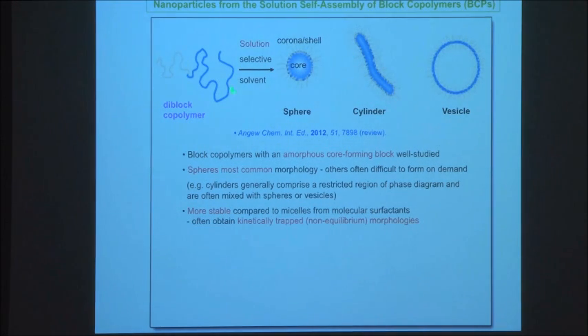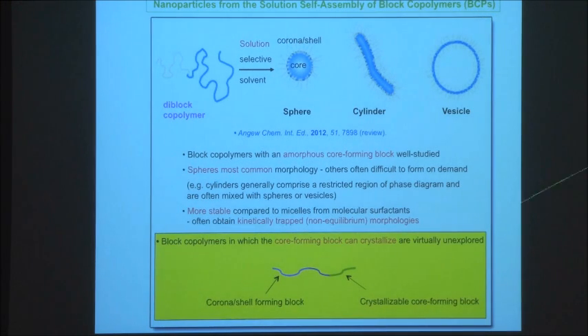So this is well explored where the core forming block is amorphous. And what I'm going to talk about is a twist on this, and it's actually a very simple twist. What we're going to look at is block copolymers where the core forming block, instead of being amorphous, can actually crystallize. And remarkably, these types of structures have hardly been looked at in the literature. We stumbled into this area really by accident. And what we found is that if the core can crystallize, you get really profound changes in the self-assembly behavior and also what you can do with the resulting structures.